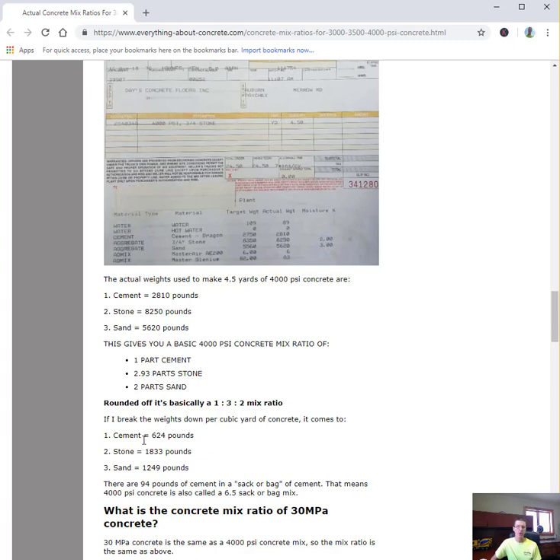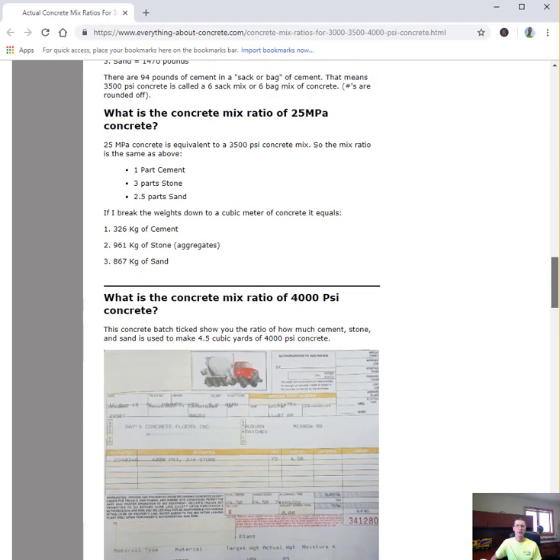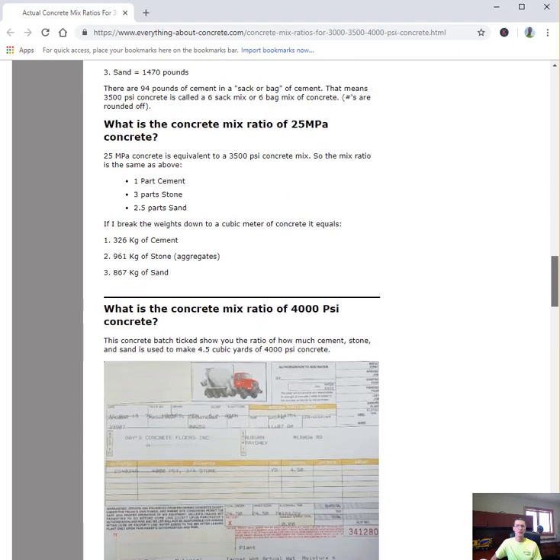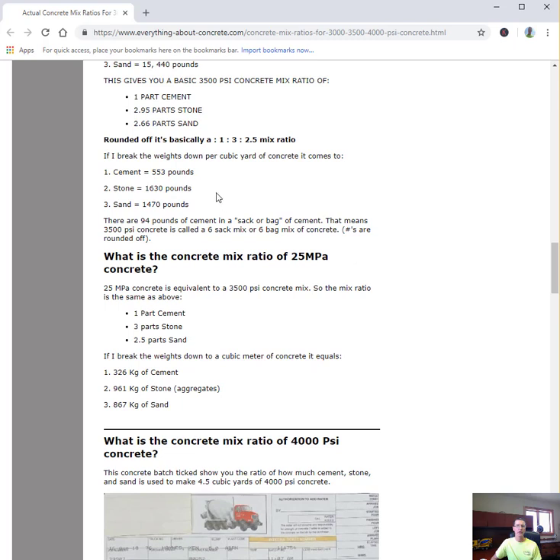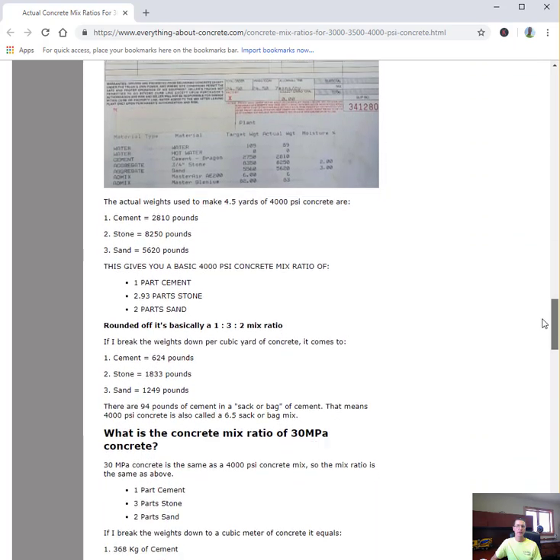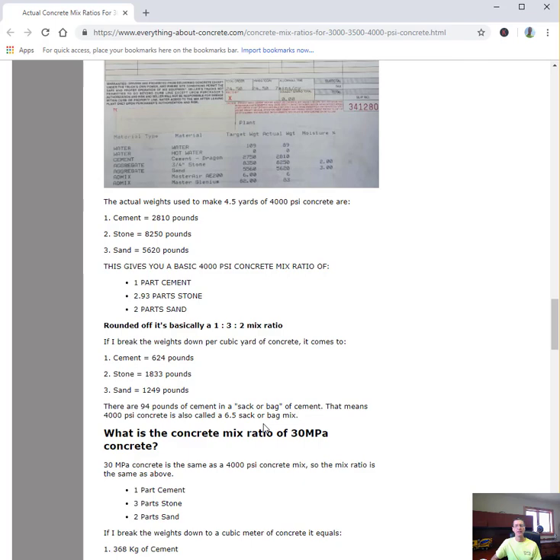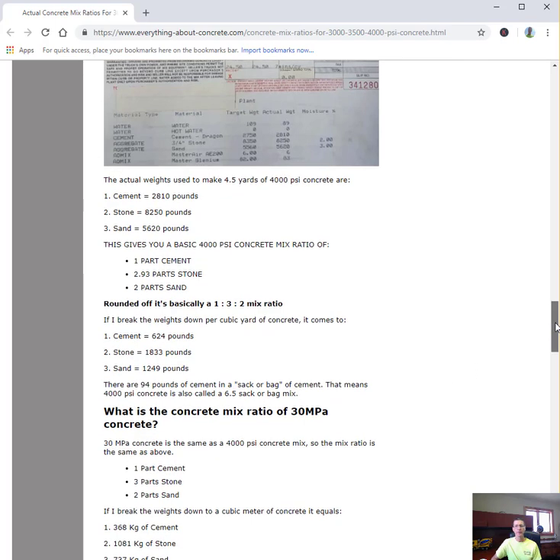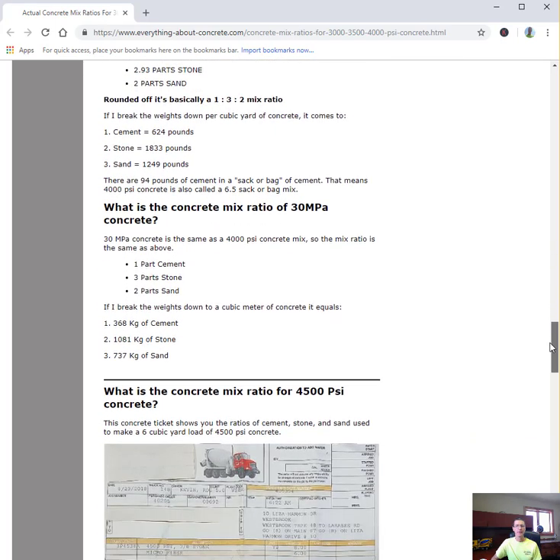I broke that down per yard for you if you need to mix about a yard of concrete - 624 pounds per yard. For a yard of 3500, there was 553 pounds of cement, and there's 624 pounds in the 4000. So that's like another whole bag of concrete. 4000 PSI mix is basically a 6.5 sack mix of concrete. 4000 PSI concrete is equivalent to a 30 MPA mix design also.